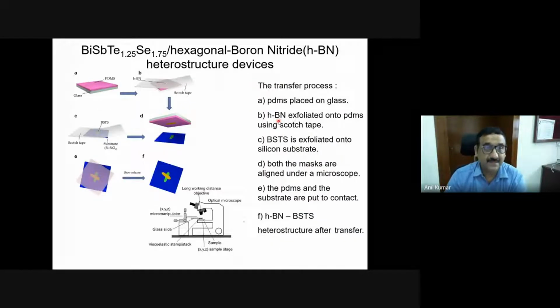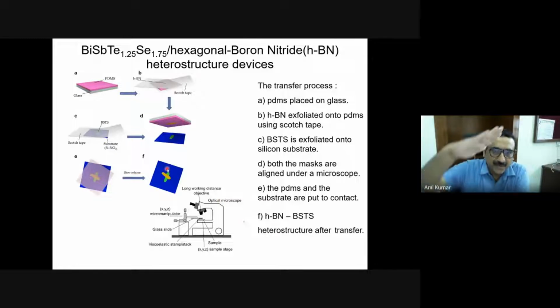Now, making is not that simple. It is of course done with exfoliation by Scotch tape. You take a glass substrate and deposit PDMS on top of it, and then with the Scotch tape, you exfoliate hexagonal boron nitride and add it to this one. At the same time, on the silicon dioxide substrate, I exfoliate BSTS, and then the two are brought together under an optical microscope. You bring them in contact, then apply a sufficient temperature so that the HBN gets released from this, and finally you get this kind of structure. Then if you remove the glass slide, you see this.